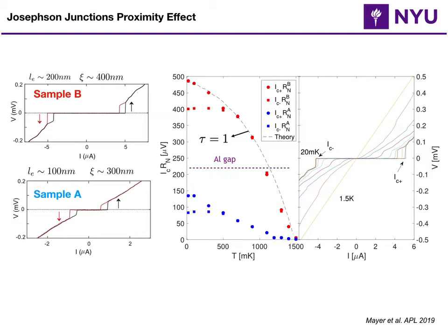And in a short ballistic limit, you theoretically expect a factor of 3 above the gap. So the aluminum gap is about 200 to 220, and that times 3 is about 600, 700, right? So the red one is really close to the short ballistic theoretical limit, while the blue one is not as good.